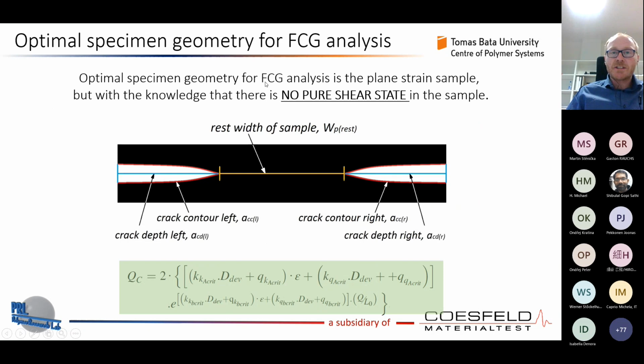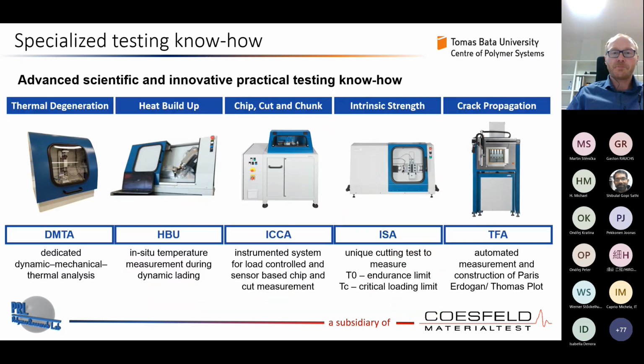The optimal specimen geometry for fatigue crack growth analysis is the plane strain sample, for sure. But with the knowledge that there is no pure shear state in the sample, you can only measure this with the knowledge of how large your deviation from this pure shear state is. Yeah? And that's a very important point.